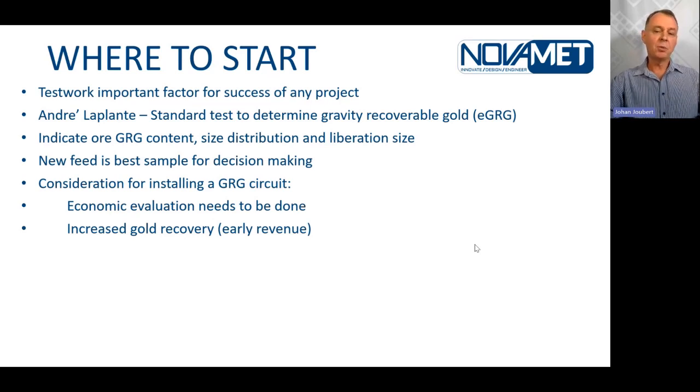Now, André also published in one of his papers that you can expect about a 0.5% increase for every 10% that you treat of a flotation circuit, and a 0.2% increase for any 10% that you treat in a cyanide circuit. So we do have some literature backup, at least for this.